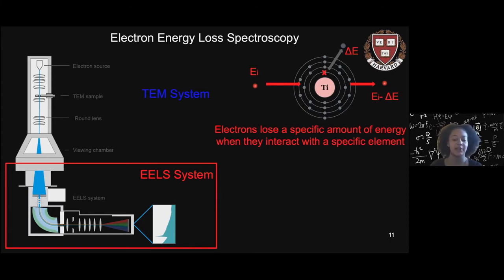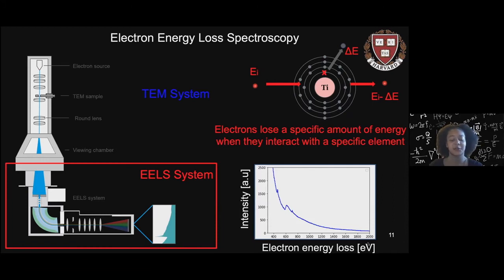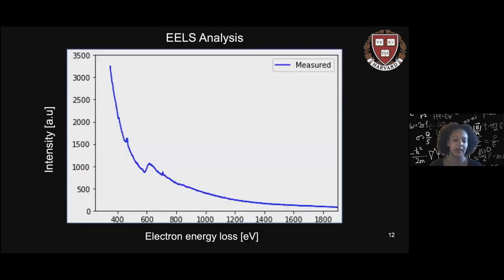With some care and looking at a wide range of energy losses, such as this curve, which is an actual data curve obtained from our EELS measurement, we're able to determine exactly which types of atoms and the number of atoms of each type that are being struck by the beam. So this electron energy loss spectroscopy technique and this data curve is essentially what we analyze to understand exactly where selenium and other elements are located in our sample.